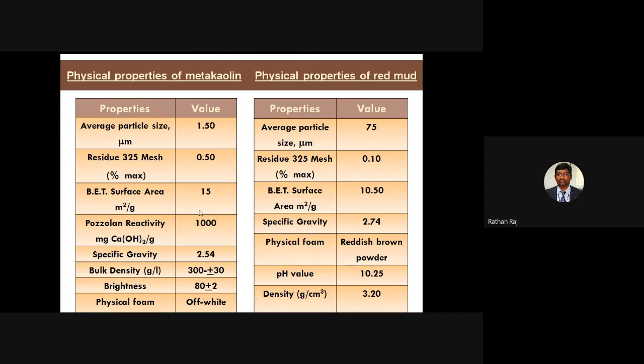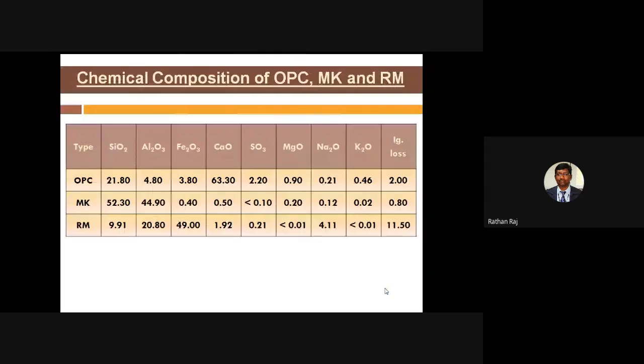to have more pozzolanic reactivity because of the silica content and calcium content present in the material. And as a physical property, the red mud has a pH value. At that particular time, that pH value is more than 10.25. So this 10.25 is maintained throughout the concrete life. Now the chemical composition of the cement, metakaolin and red mud.